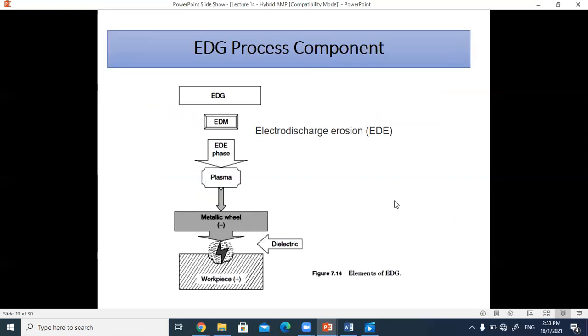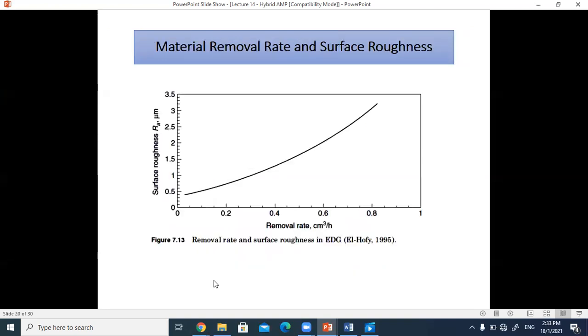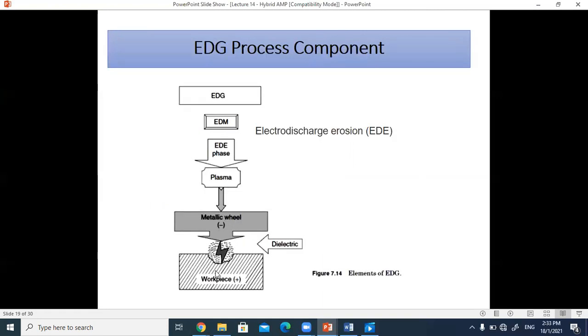So in terms of EDG process components, basically you have the EDE phase, which is the electrode discharge erosion phase. So in the EDM process, basically you have the electrode discharge erosion phase. So the erosion happens due to the electrode discharge. And in this particular case, you have a plasma, and the plasma is developed between the metallic wheel and the workpiece. So the metallic wheel is negatively charged, and the workpiece is positively charged, and in between you have a dielectric. So when you have such a situation, if the voltage differential and also the gap between the workpiece and the tool is adequate, then you're going to have a spark. Right? And that spark causes erosion and melting or vaporization of the workpiece material.